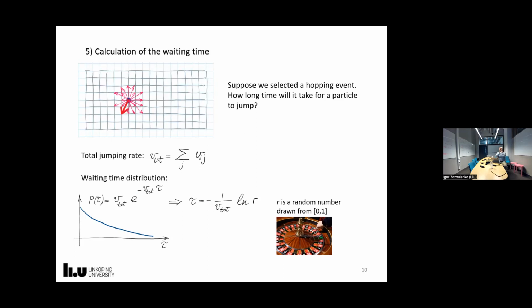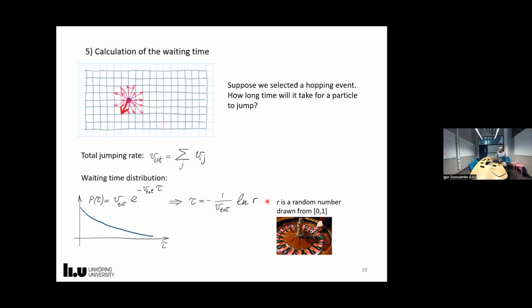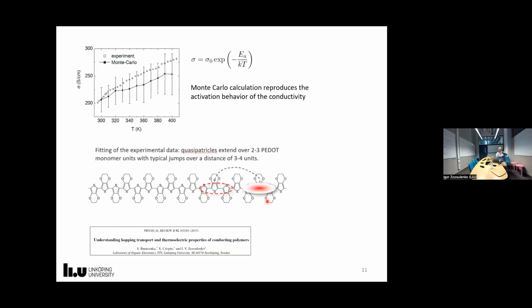Okay, as a next step, we calculate the waiting time. Suppose we selected a hopping event, but then how long will it take for the particle to jump? There is a simple formula which gives us the waiting time distribution. Again, we run this Monte-Carlo: we choose some random number, we choose a particular waiting time, and that's it. So we have everything. Using this Monte-Carlo for each particle, we trace particle motion in our system and, using the prescribed rules, we calculate the current. And these are the results.